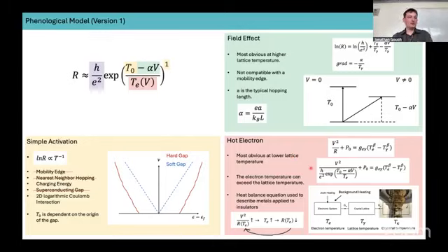Unlike metals, a strongly localized system is strongly dependent on the electron temperature. So you get this very unusual feedback mechanism occurring, where as your joule heat, V squared upon R, shown down here, increases with applied voltage, your electron temperature then increases, which then lowers your resistance significantly, which then comes back and increases your joule heat. So above a critical voltage, you get this very unstable regime where your electron temperature can very suddenly increase.